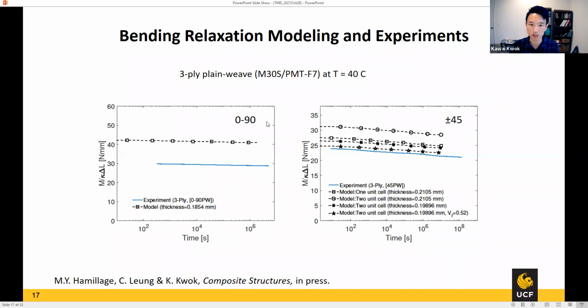On the left-hand side is the 0-90, right? So the fibers are along the bending direction. On the right-hand side is plus or minus 45, so that is 45 degrees from the bending direction. What you're looking at is the moment divided by the imposed curvature and the length of the unit cell or the sample, as a function of time. In the 0-90 there is not a lot of relaxation because it's dominated by fibers.